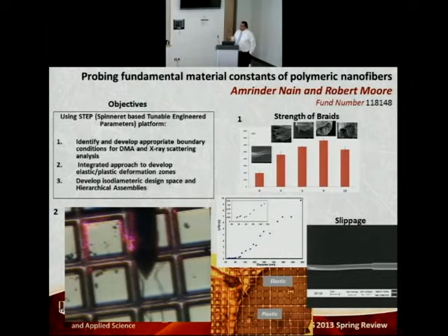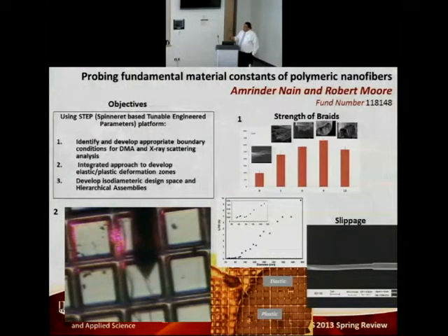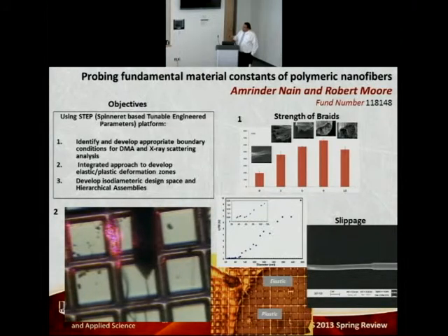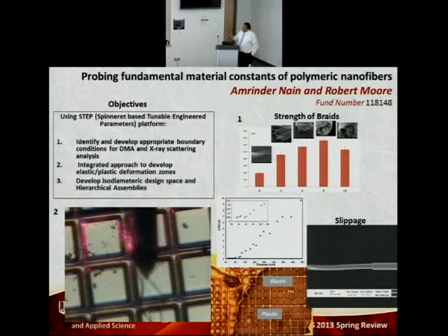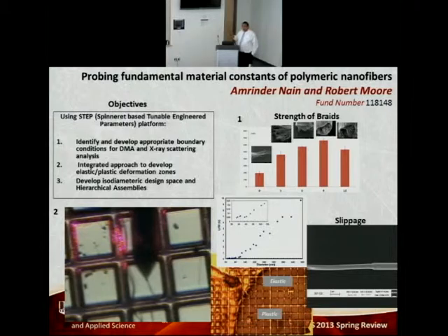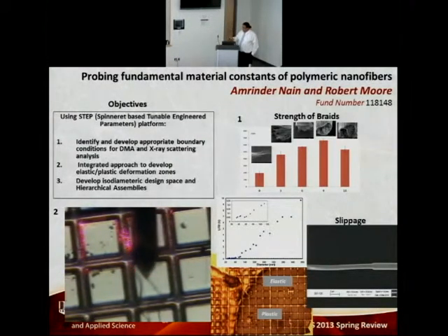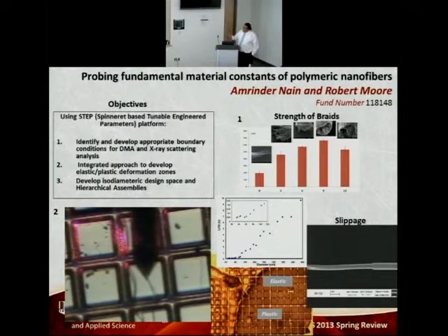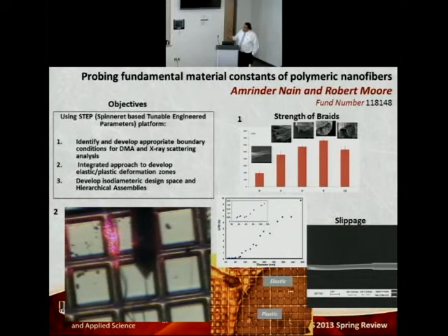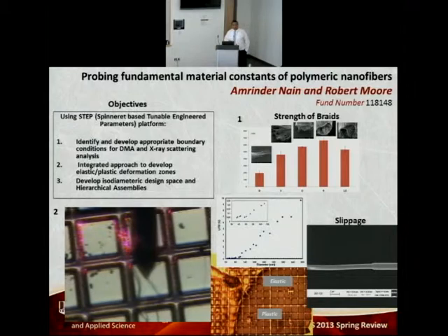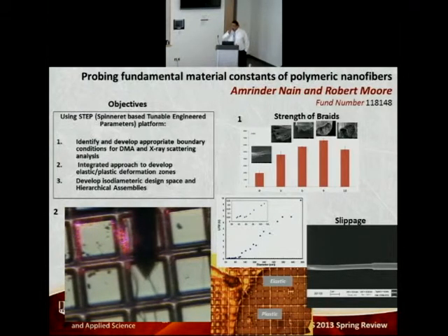We have demonstrated that we can take this fiber and really scale it down to nanoscale. This is a plot of the diameter and the breaking force from the AFM to break individual single fibers suspended onto TEM grids. The inset shows that the smallest diameter fiber we have broken is around 30 nanometers in diameter.